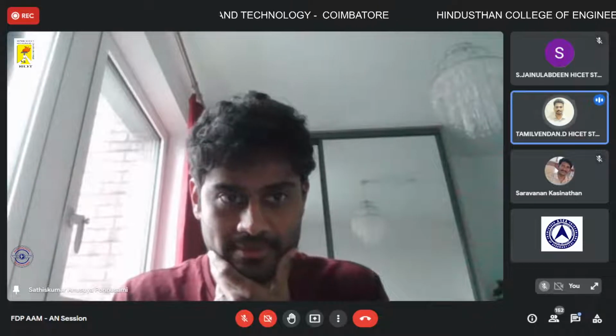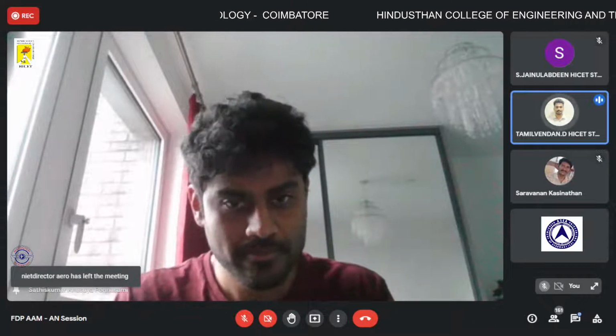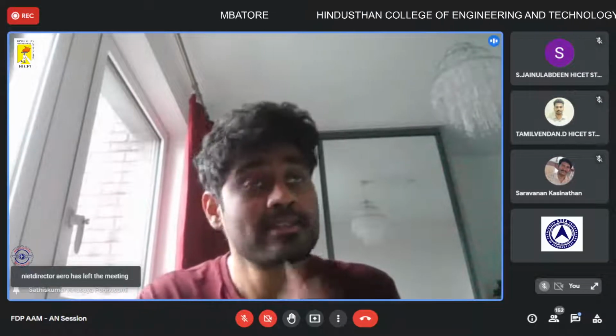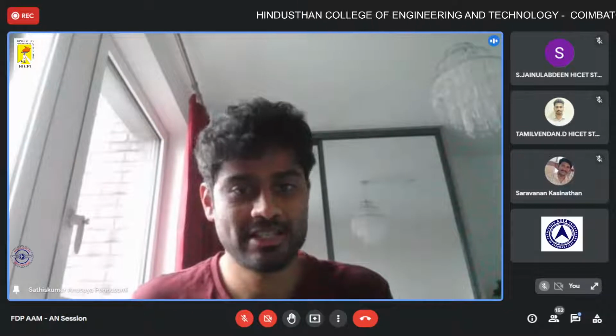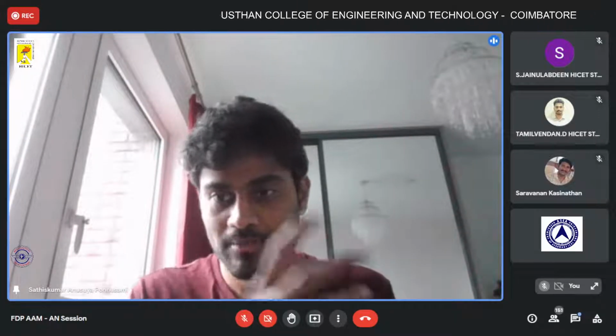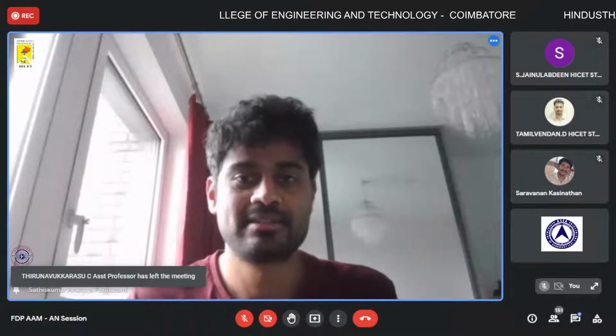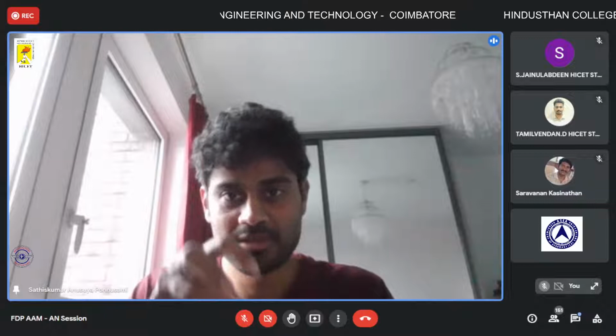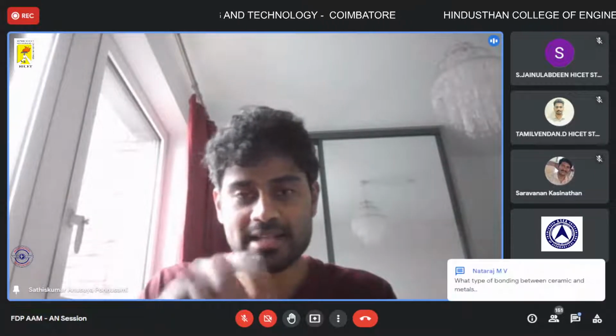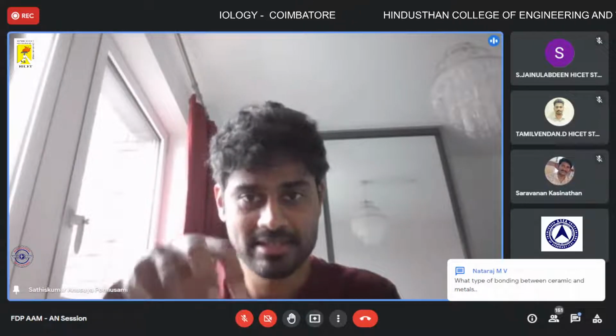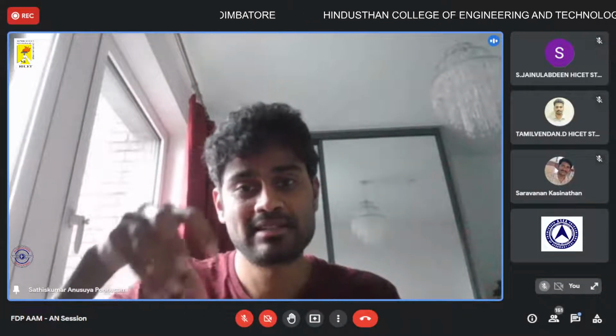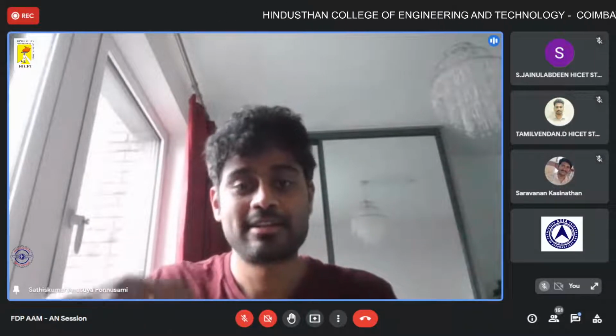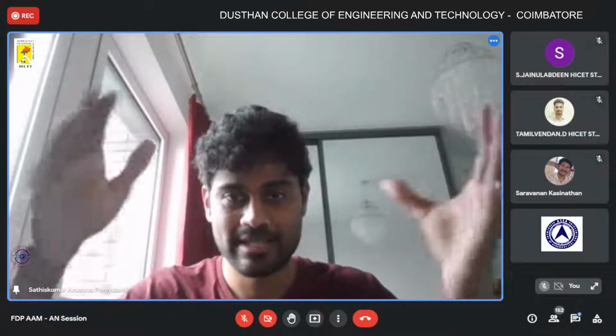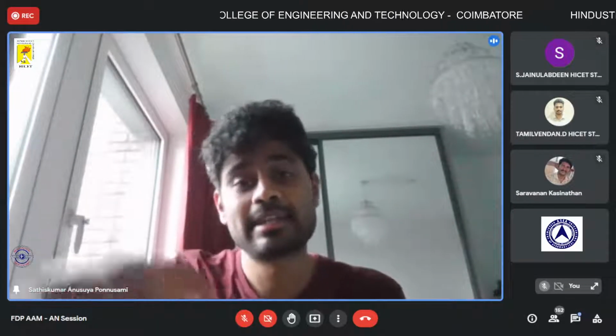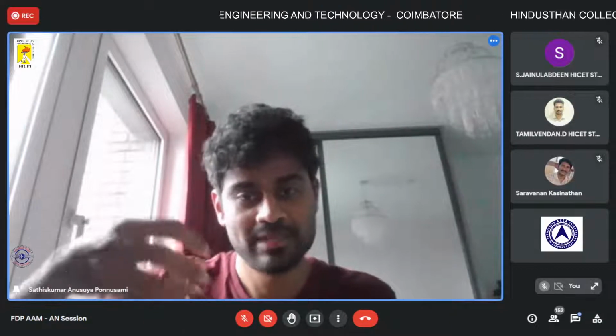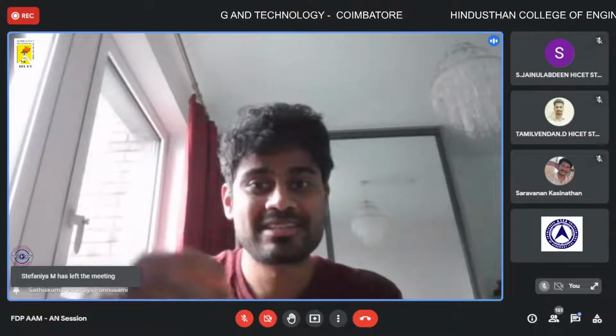Is there any idea about the type of agent, the materials? The specific agent is made of molybdenum disilicide, MoSi2, and the top coat, the ceramic coating, is yttria stabilized zirconia. When a crack is formed, the molybdenum disilicide particle is exposed to the air, and the silicon in this particle gets oxidized because you have oxidizing air at high temperature. This silicon forms silicon dioxide, SiO2, commonly called silica, which expands and fills the crack.